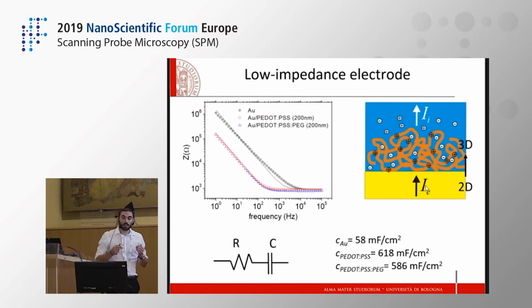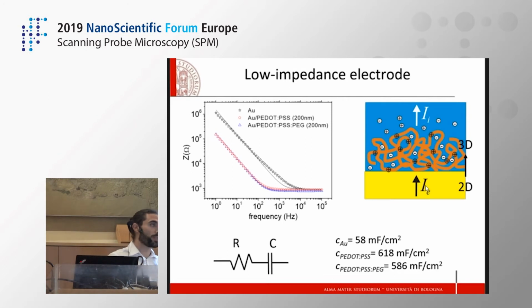Here is presented the impedance of our electrode before and after the coating with the two different polymers. In particular, we use an RC circuit in series to model the system. The R stands for the electrolyte resistance, for the flat response at high frequency, while the C is for the ionic double layer at the low frequency of the spectra. By depositing the PEDOT, we move from a two-dimensional metallic interface to a three-dimensional polymeric one, thus enabling also the ionic conductivity in our electrode.